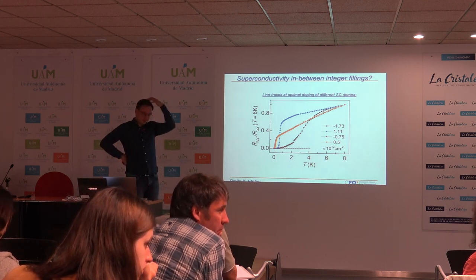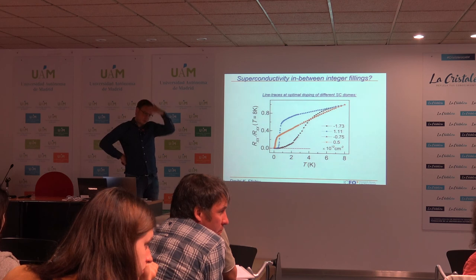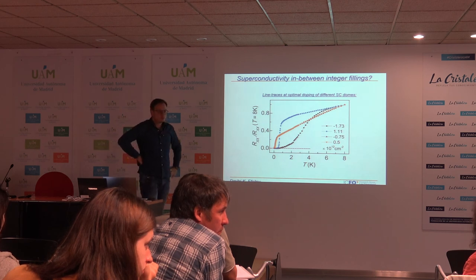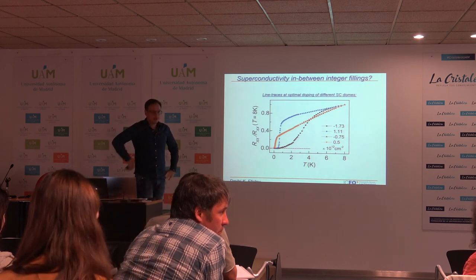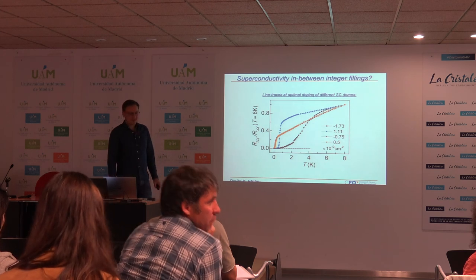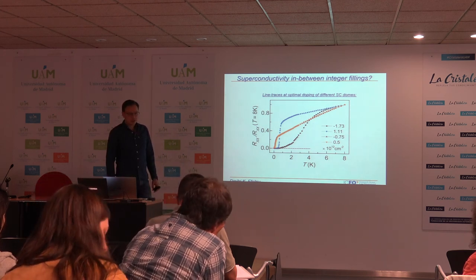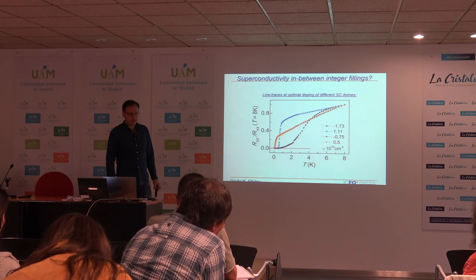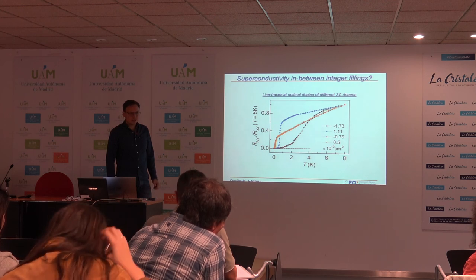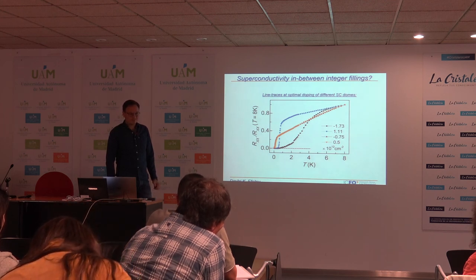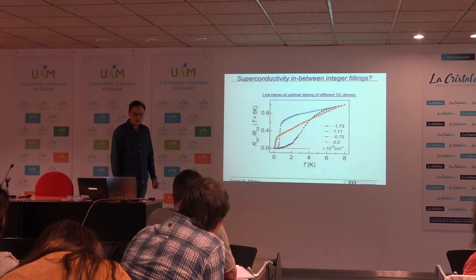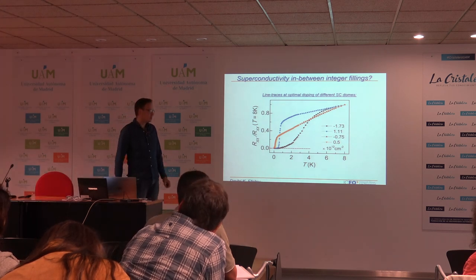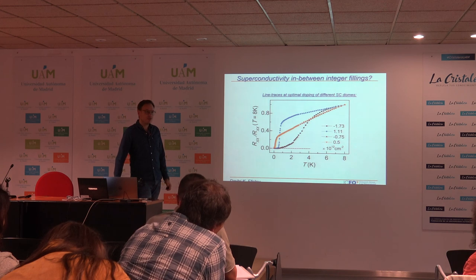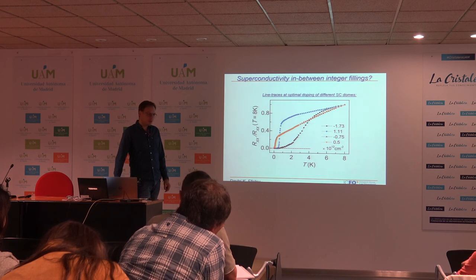Maybe you mentioned this, but how much does it correlate experimentally in the samples of the different groups to observe these ferromagnetic tendencies at three electrons, I think it is, and to have a gap at the charge neutrality point? In Young's result, they have a large gap at charge neutrality, and they have coupling to the hBN.